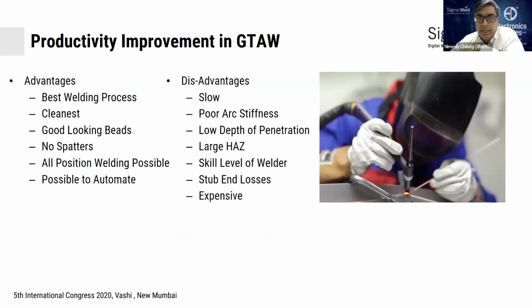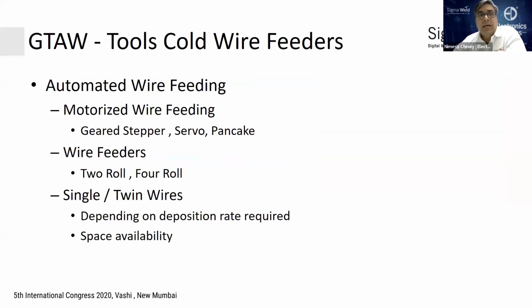Of course, TIG welding being one of our core focuses to improve the speed in, because it's one of the best processes, cleanest, most good-looking beads, no spatters, all position welding possible. It's also possible to automate. However, it comes with inherent disadvantages of being slow, having poor arc stiffness, low depth of penetration, higher heat affected zone, and of course, you need skilled welders. Can result in stub losses. Due to all this, it's considered to be an expensive process. However, there are tools that help you make this easier.